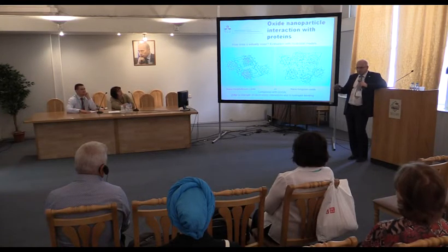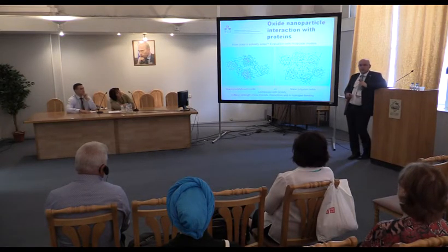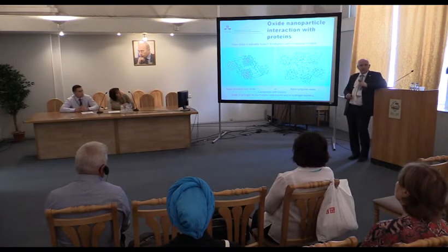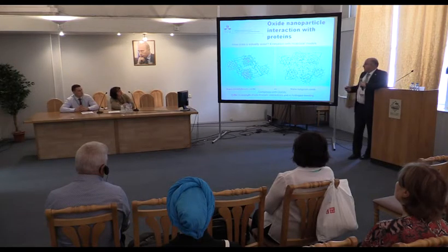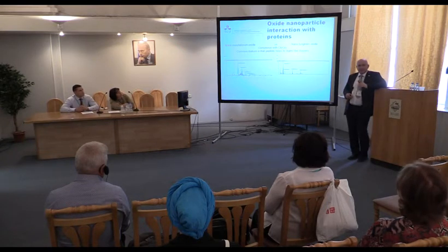It was the positively charged ammonium group which was turned towards the anion. And in the case of tungsten, the behavior was very different, because it was mostly hydrogen bonding between the protonated peptides themselves and also with the anions of phosphotungstate. And this really is a considerable difference. What we also were able to see was that the anions were not staying intact. It's very exciting, because people usually still appreciate these anions as a final step.